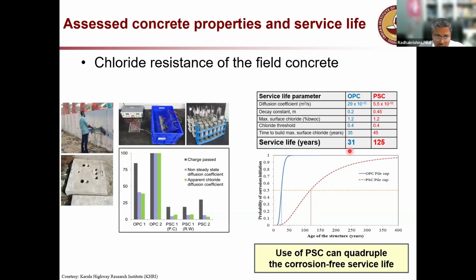So huge difference. So the idea is, you can see this graph here, the speed by which chloride will penetrate. In the OPC concrete, it's very high, whereas in the slag-based concrete, it was very, very low. So this is the advantage. You are reducing the ingress rate of chlorides and also increasing the chloride threshold. And eventually with admixtures like corrosion inhibiting admixtures, etc., you are able to get very, very long service life. That means if this is 125 here, let us say, forget the calculation, at least we'll get 100 years of life where you don't have to worry about corrosion. So this is something which I would like to emphasize, that use of supplementary cementitious materials really enhances the life of concrete structures. Okay.